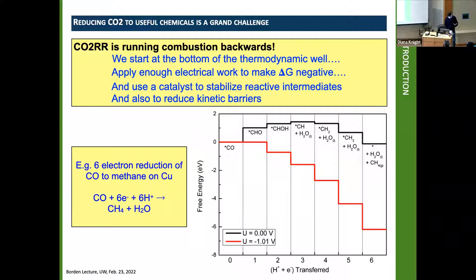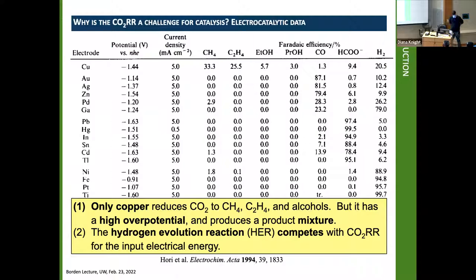This is on a copper surface, and as you'll be seeing in a few moments, copper is an especially significant metal, at least at this stage of our understanding of the CO2 reduction reaction. Why is copper so significant? This table summarizes classic experimental data from Hori's group, showing you why. The columns here are organized by the product made by electrocatalysis of CO2 and protons over copper as the cathode. If you look at the methane column, you see that copper is by far the best, 33% Faradaic efficiency going to methane. Almost no other metal will do it.